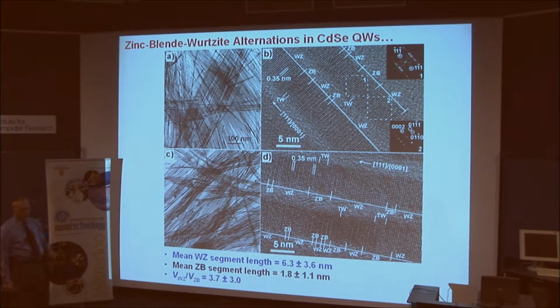I'd like to eliminate this sort of zinc blende wurtzite alternation if I could figure out how to do it, because I think it probably limits the optical properties. I think that at each of these interfaces between zinc blende and wurtzite regions, there are probably surface defects introduced. I don't have any proof for that. That's speculation. But other than this sort of structural alternation, the wires are single crystal in character.